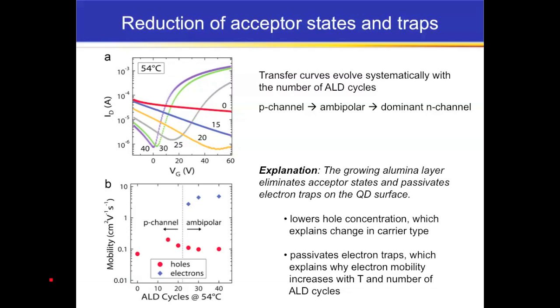As we increase the number of ALD cycles, we see that this carrier density falls, the current falls by quite a bit. And also we see the grow-in of an N channel. So at 20, we kind of get the beginnings of an N channel. At 25, we have an ambipolar kind of transistor. And then at 30 and 40 cycles, we have a dominant N-type transistor. So we go from P channel and we tune through ambipolar to dominant N channel.